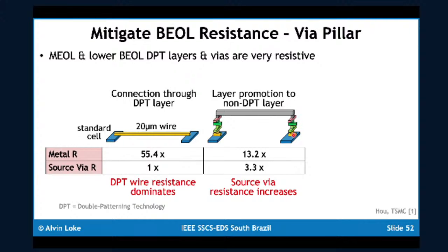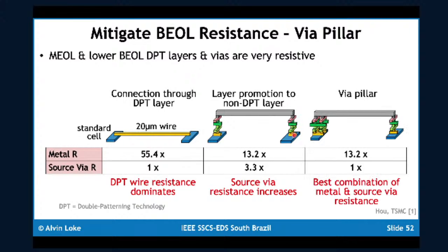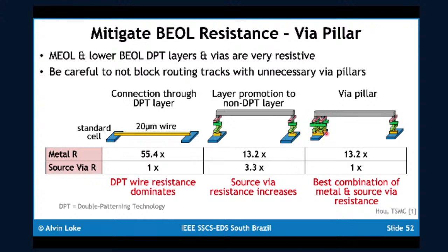In the process of doing this, you do eat the burden of having more series resistance in via resistances getting up and down. However, if you were to create these via pillars to reduce your via connectivity resistance, you can actually end up with a much lower overall resistance. The downside, of course, is you have to pay attention that you don't block precious routing tracks with unnecessary via pillars.